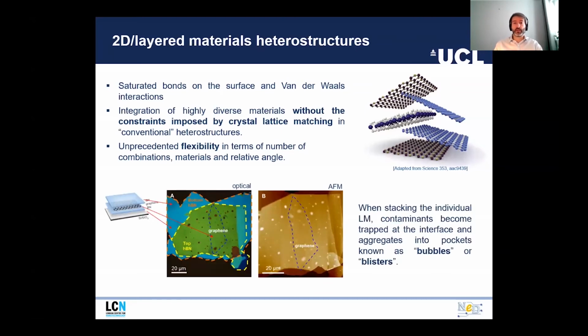When we started working on heterostructures, the very first problem we had to face was that when we combine different materials, impurities and contamination get trapped at the interface, and they form the so-called bubbles and blisters. In any heterostructure, the device is at the interface, so we really had to make sure that the interface was of the highest possible quality. So the first problem was how to clean the interface.